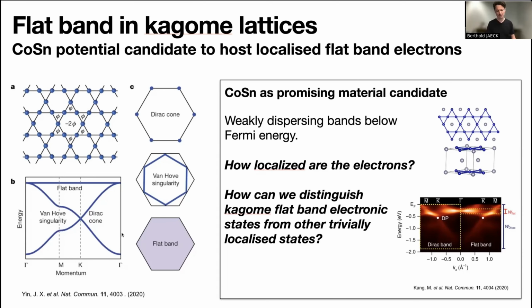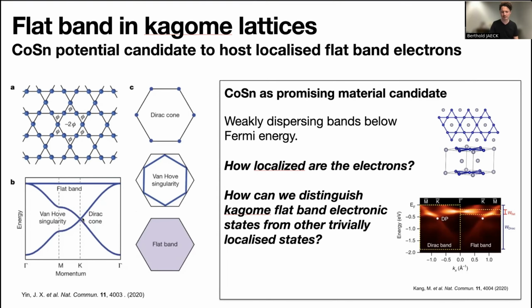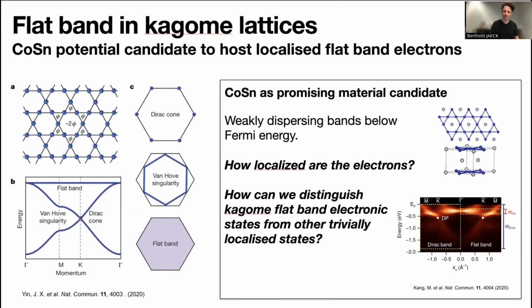What you see here is essentially the model calculation of a single s-orbital per lattice site Kagome lattice, right? It has basically one flat band, and the other two bands giving rise to the Dirac cone. In reality, the situation is more challenging.